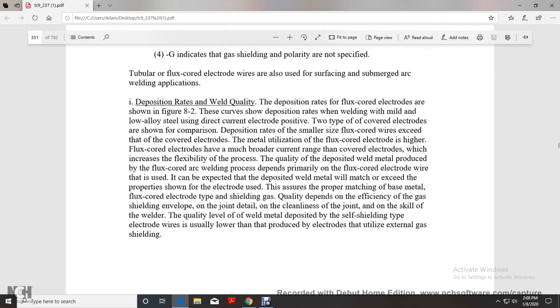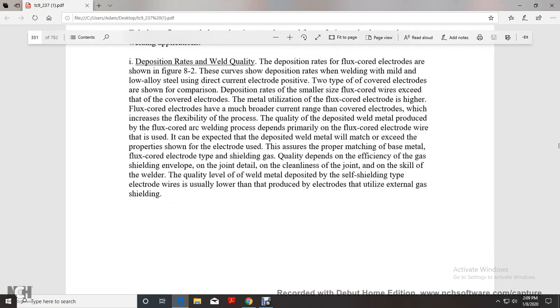Deposition rate and welding quality. The deposition rate of flux core arc welding is shown in figure 8-2, with curves of the deposition rate for welding mild and low alloy steel with direct current electrode positive. Two types of covered electrodes are shown for comparison. The deposition rate of a smaller size flux core wire exceeds that of the covered electrode. The metal utilization of flux core electrode is higher, and the flux core electrode has a much broader current range than the covered electrode, which increases the flexibility of the process.